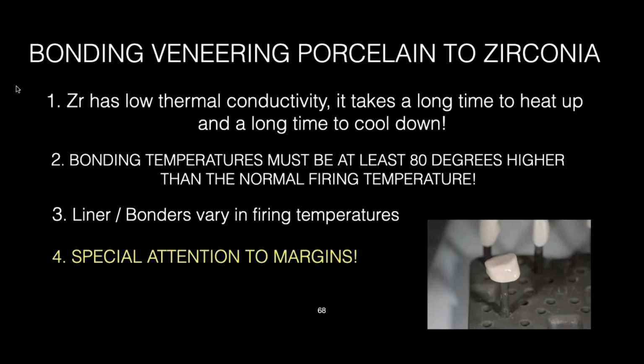So remember, repeating, zirconia has a low thermal conductivity. It takes a long time to heat up and a long time to cool down. The bonding temperatures must be at least 80 degrees centigrade higher than the normal firing temperature. The liners and bonders also vary in temperature, so you have to keep an eye on that. And special attention to the margins.